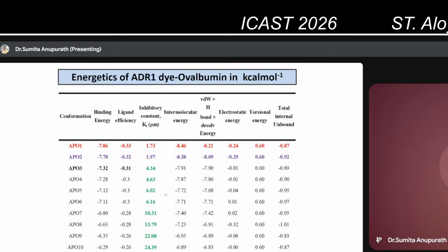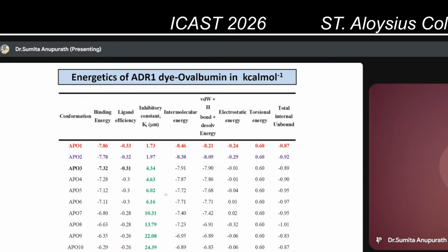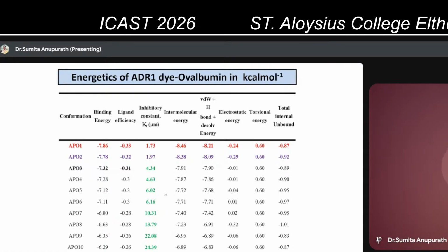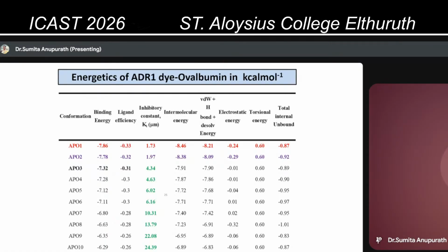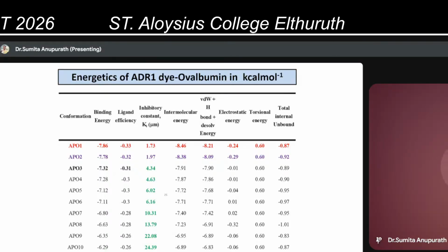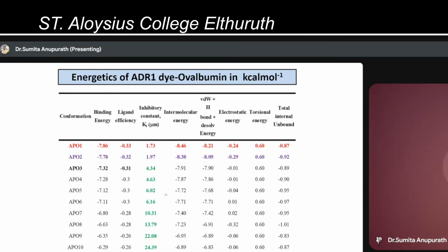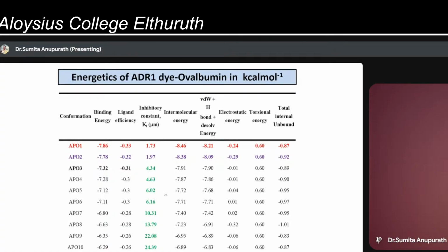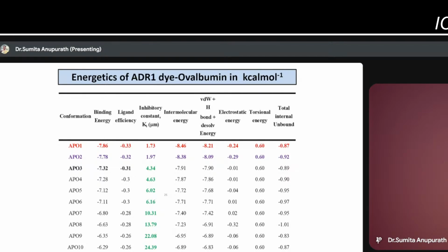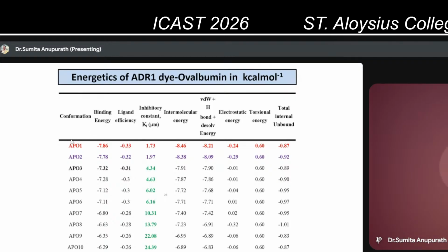Further, to validate our findings, molecular docking studies were carried out, and with the help of those theoretical studies, we were able to calculate the energetics of the dye-protein complex. So we generated 10 conformers between the ADR1 dye and ovalbumin based on their stability, and various other parameters were also calculated: binding energy, ligand efficiency, inhibitory constant, etc. And based on these values, we found that one particular conformer was the most stable conformer.